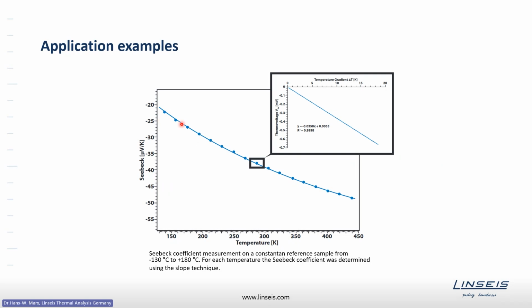Every dot which you can see here on this graph was obtained by using the slope method, so applying different temperature gradients and measuring the thermal voltage at different gradients. And the slope, in this case a negative slope of 36 microvolt per Kelvin, is the Seebeck coefficient. It's a negative one in this case.